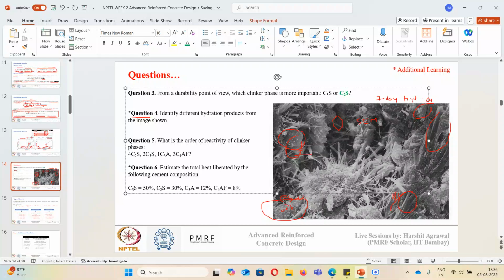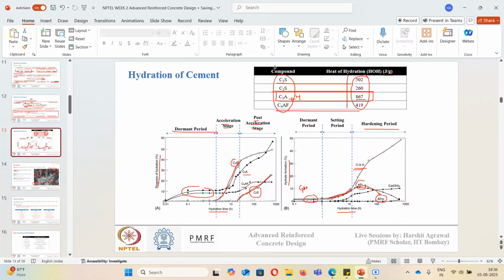Estimate the total heat liberated. This is a very simple question. Here we have the table. I will just paste the table here. Here I can see the values. What we need to do is multiply the composition of cement with the amount of heat liberated. Suppose I have 1 gram of cement, in which I have 50% C3S, 30% C2S, 12% C3A, and 8% C4AF. So per gram, we know how much heat is liberated.